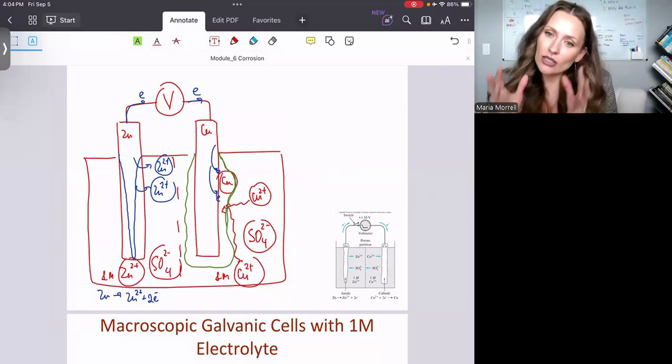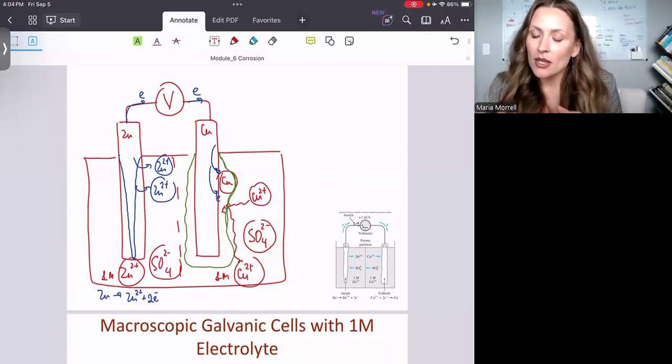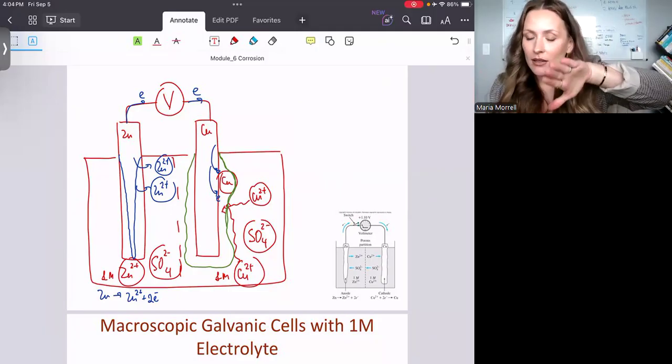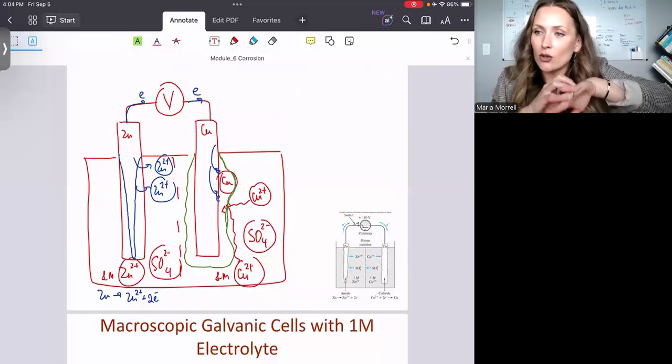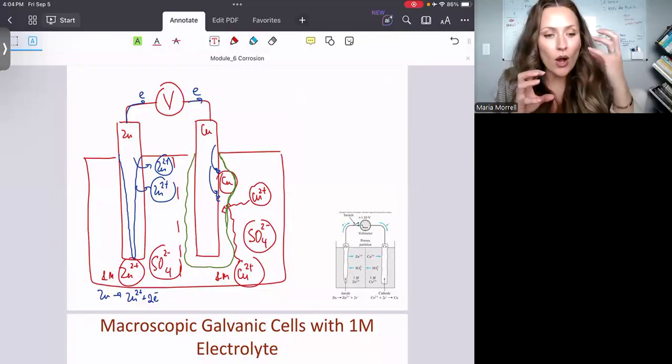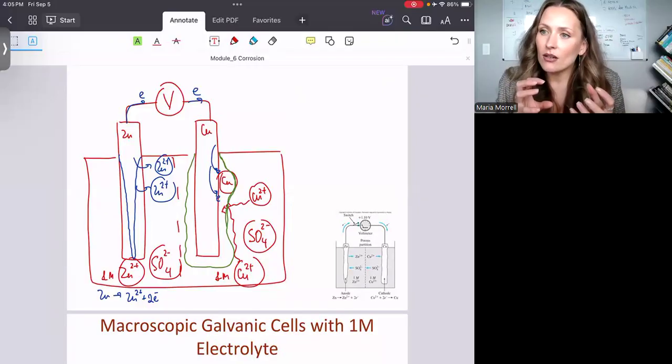And I know that right now you're looking at the example and you're probably thinking like, okay, so what's the problem? The problem is, if I have a plate and if I use the wrong bolt, and if I put this bolt in and all of a sudden these two are different, one is cathode, another one is anode, regardless of which one is which, you don't want any materials to corrode. Now, the first rain happens where moisture is trapped in between. Here's your electrolyte. These two are now in intimate contact, right? So electrons will be floating.